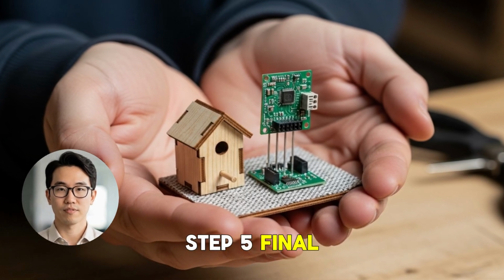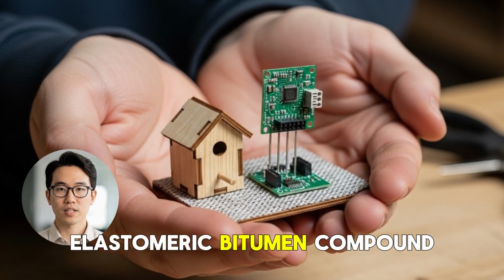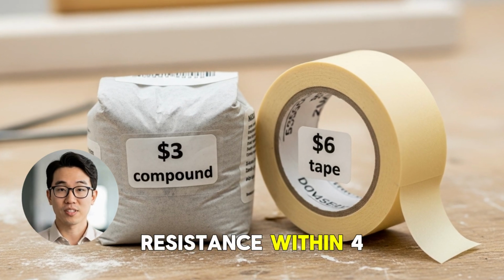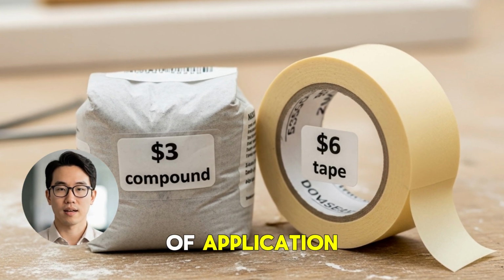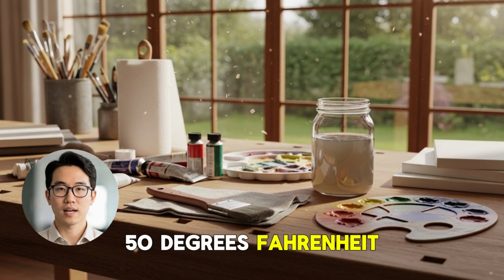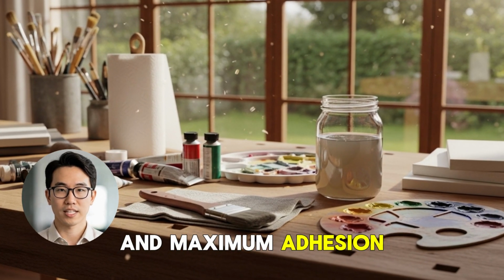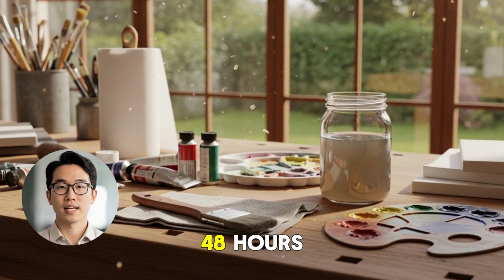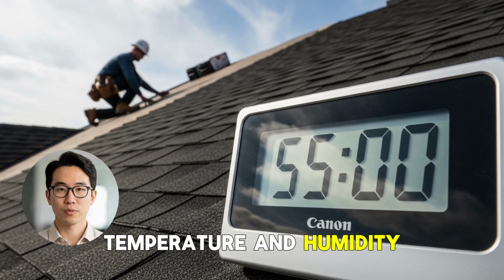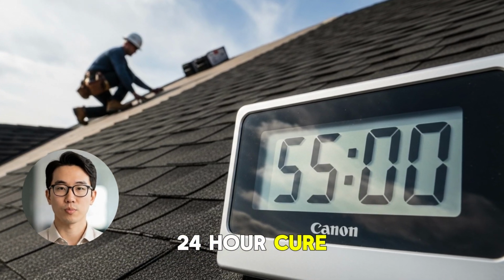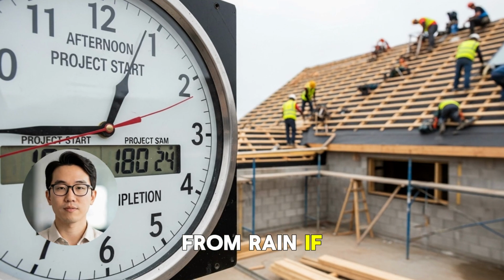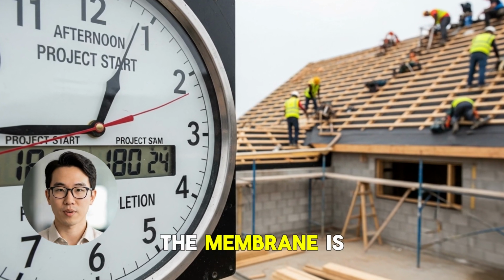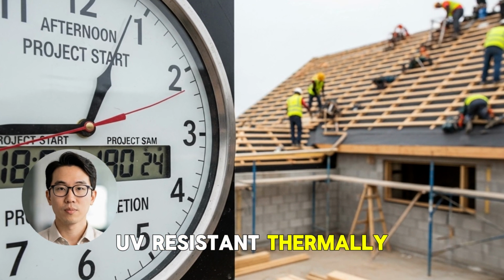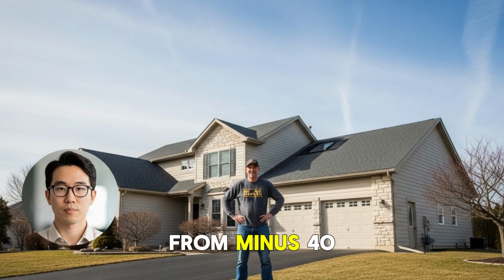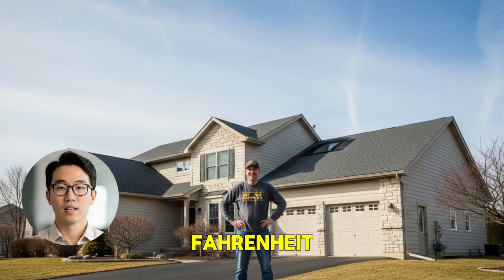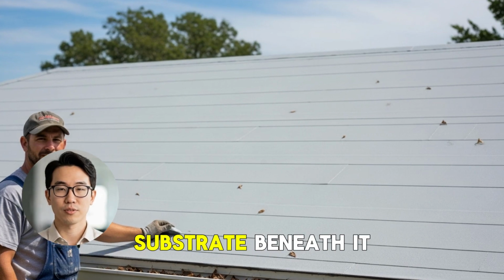Step 5. Final cure. Elastomeric bitumen compound reaches initial weather resistance within 4 to 6 hours of application in temperatures above 50 degrees Fahrenheit. Full membrane cure and maximum adhesion strength is reached in 24 to 48 hours, depending on ambient temperature and humidity. During the initial 24-hour cure period, protect the application from rain if possible. After full cure, the membrane is waterproof, UV-resistant, thermally flexible across temperature ranges from -40 to 250 degrees Fahrenheit, and permanently bonded to the roof substrate beneath it.